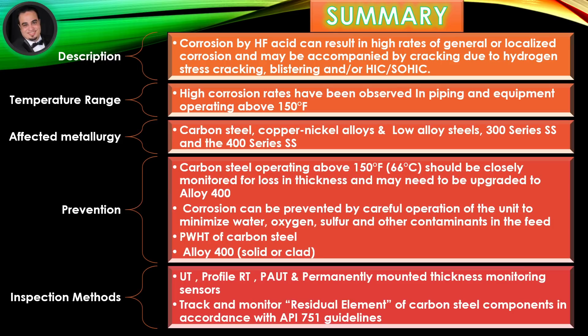Summary — Description: Corrosion by hydrofluoric acid can result in high rates of general or localized corrosion and may be accompanied by cracking due to hydrogen stress cracking, blistering, and/or hydrogen-induced cracking and stress-oriented hydrogen-induced cracking. Temperature range: High corrosion rates have been observed in piping and equipment operating above 150 degrees Fahrenheit. Affected metallurgy: Carbon steel, copper-nickel alloys, low-alloy steels, 300-series and 400-series stainless steel.